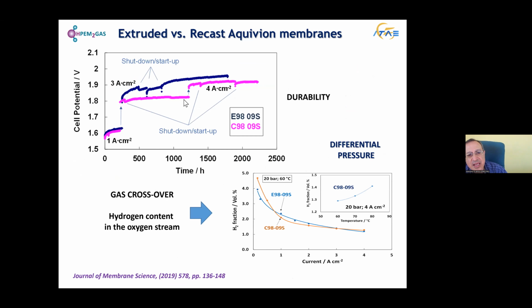But regarding stability, we can clearly see that the cast membrane is better performing than the extruded membrane, with lower cell voltage at the same current density. With the cast membrane, we can reach a current density of something like 4 ampere per square centimeter. But there is another aspect to consider.